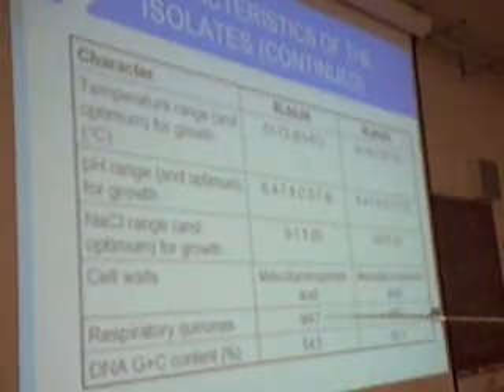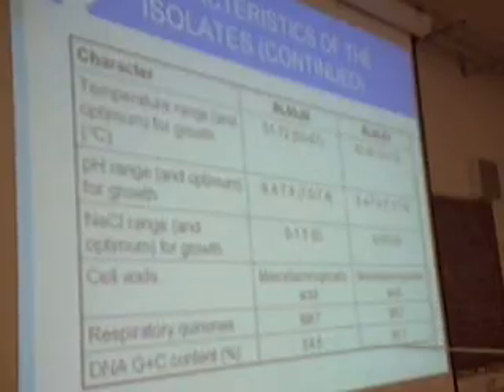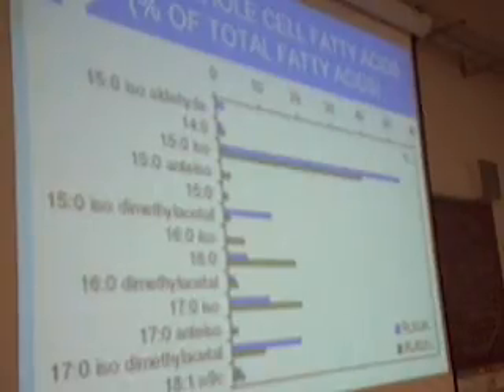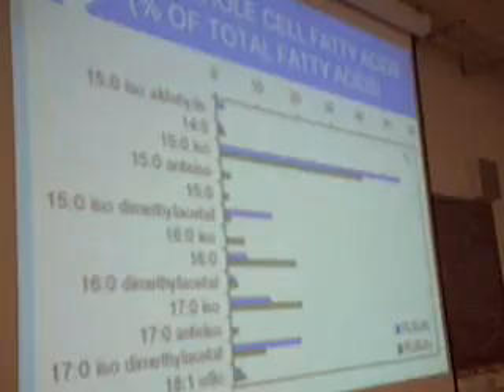And both liked a neutral pH range, but did not tolerate very much salt. Then we also analyzed the cell walls and respiratory quinones. Meso-diaminopimelic acid was the main component of the cell walls, and menaquinone 7 the respiratory quinone. And the DNA G plus C content was 54 and 60 for the strains. Then major whole cell fatty acids are shown here. The most dominant was 15:0 iso fatty acid, and in general most of the fatty acids were saturated, as is common for many thermophiles.